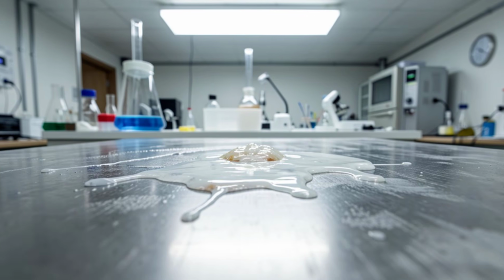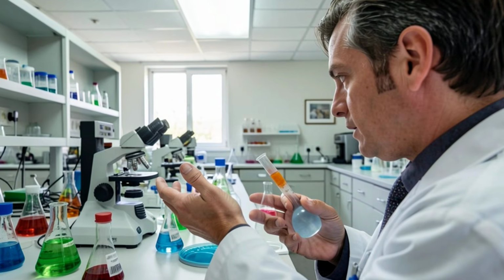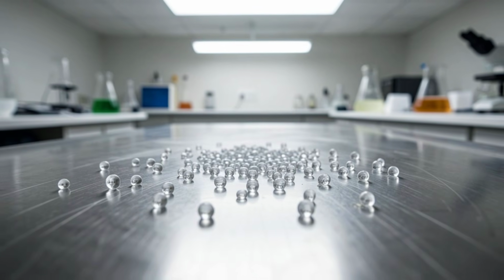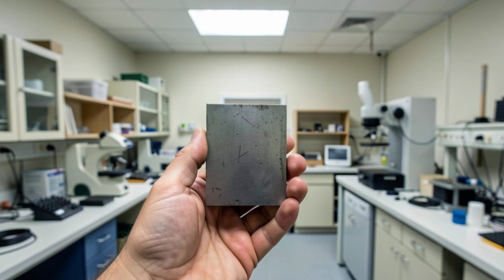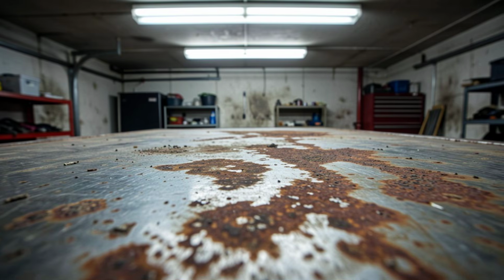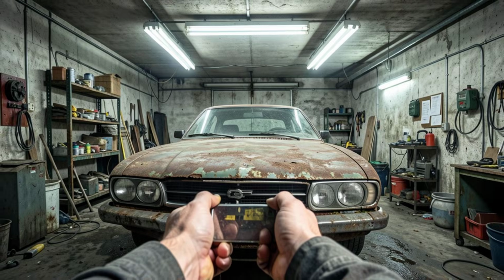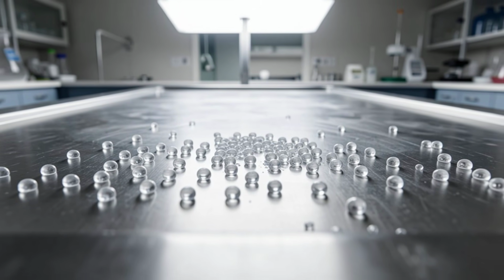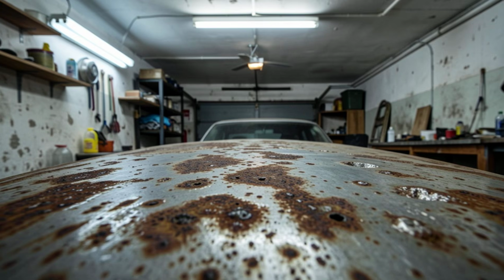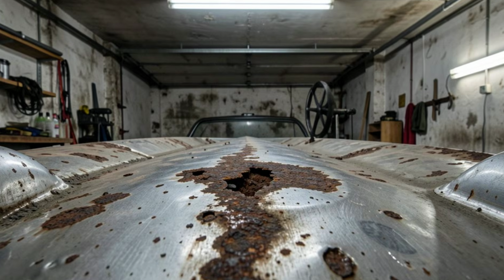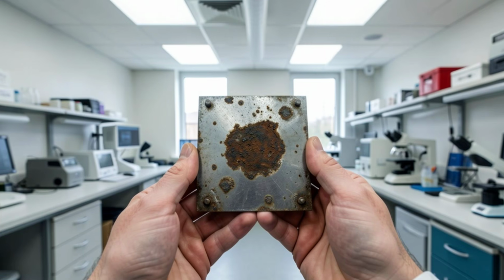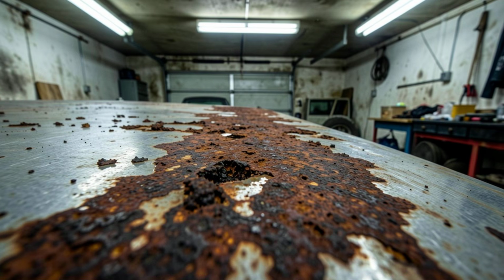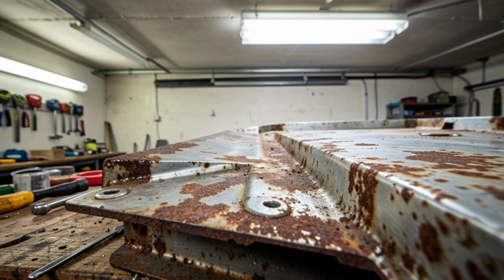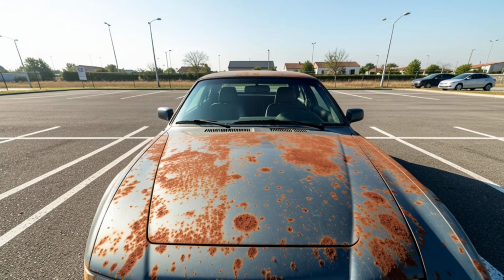The chemistry behind this step is as important as the chemistry of the treatment itself. The chloride ions that made this protocol so effective, the same ions that broke down the passivation layer and allowed the acid to penetrate deeply, are still present on your metal surface after you wipe away the iron acetate slurry. Chloride ions on bare steel do not simply evaporate, they remain active, and on an unprotected steel surface, they initiate an electrochemical corrosion process called chloride-induced pitting corrosion that is significantly more aggressive than normal atmospheric rust formation.